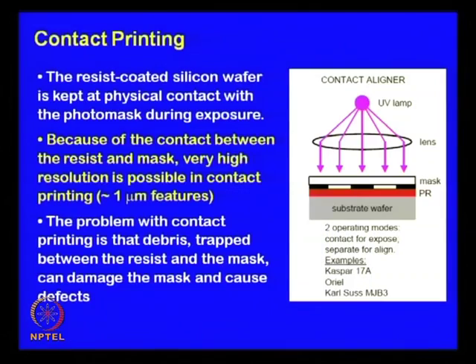So, what is going to happen? The dust particle sitting on the film surface, that photoresist surface, or on the mask will prevent the two of them coming in conformal contact, and that will destroy the pattern transfer completely. So, this is a classic example where you can realize how a dust free environment is extremely important for proper implementation of photolithography. Because the mask is in contact with the resist, very high resolution is possible.